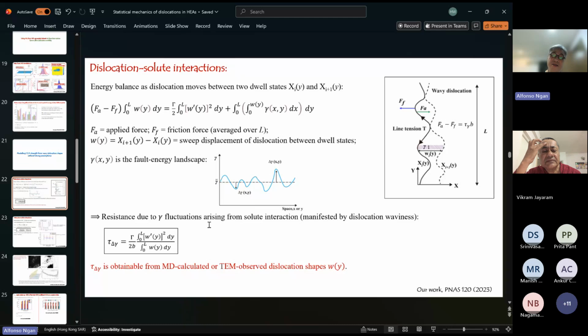So in the case of a pure metal, the gamma would not be fluctuating. It will be a flat line over space, so the W prime would be zero. The dislocation should be straight or mostly straight, then this tau delta gamma should be 0. So this term would not be there for pure metals. And that's the idea of the whole analysis.